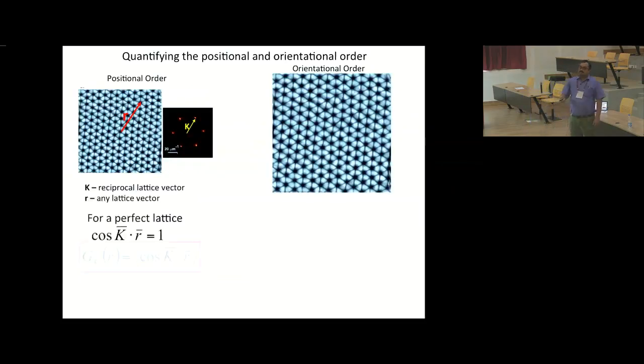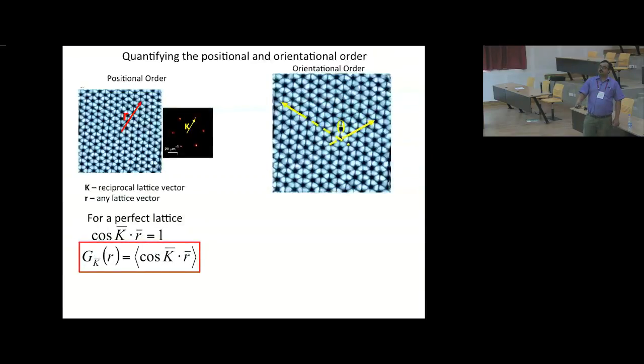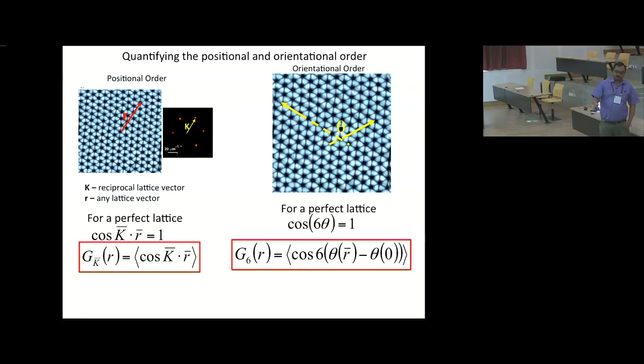So one way to quantify this is to look at the positional and orientational correlation functions, where you take the reciprocal lattice vector. For the positional order, you can quantify it through the quantity cos(k·r). If k is a reciprocal lattice vector and r is a lattice vector, then you know that this has to be 1 for a perfect lattice. If it is an imperfect lattice, it can be smaller than 1. So you average over all the possible r's that you have within your range. Similarly, to quantify the orientational order, you look at two bonds separated by a distance r, and if the angle between these two bonds is theta, for a hexagonal lattice cos 6θ should be 1, and you do this average over all possible pairs of bonds.